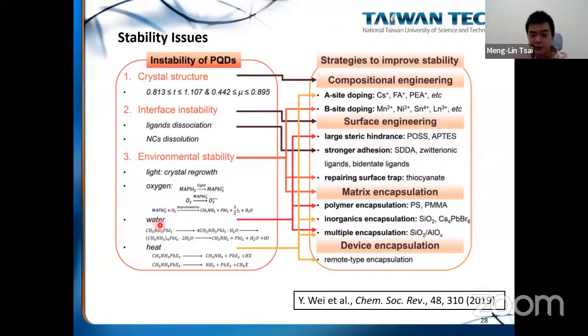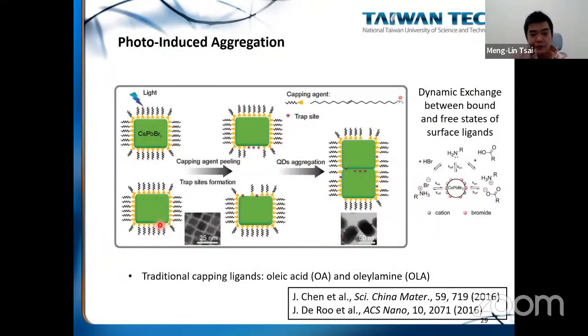from oxygen or water. This slide shows the photo-induced aggregation process for quantum dots. If we have two neighboring quantum dots under light excitation, since the interaction between your ligand and the quantum dot is not very strong, sometimes your ligand will come off. And if you have two neighboring quantum dots, they will grow bigger. This is called QD aggregation. If it grows bigger, then the quantum confinement effect is lost, so your quantum yield will drop.